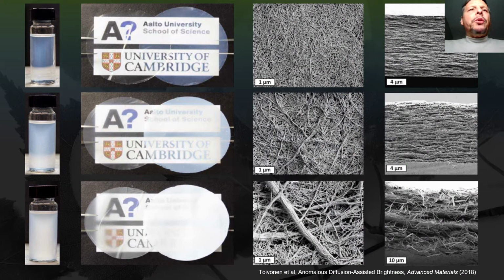My point here is to report about how these fibrils that are produced can be placed into a two-dimensional film or a nanopaper in this case. And those nanopapers, as you go from top down, they can be extremely transparent, so top left, to extremely opaque, bottom right. And those papers are produced from the same basis weight. On the far right, you can see the networking structure of the fibrils, going from the finer ones on top down to the coarser ones. And that would be a plain view together on the far right with a cross-section of the material.